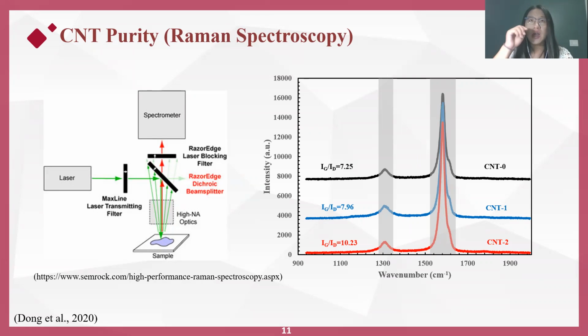Under identical conditions, IG over ID has increased by the addition of water from 7 all the way to over 10. And this CNT quality improvement could possibly be attributed to the effectiveness of catalyst cleaning by removing the amorphous carbon. We also note that the G band exhibited an asymmetric line shape with a weak peak appearing at 1590 per centimeter. This is likely associated with the large amount of multi-wall carbon nanotubes, due to the diameter variations among different nanotubes. This asymmetric feature became less conspicuous as the water concentration increased, suggesting a narrower diameter distribution of multi-wall CNTs with fewer disorders.